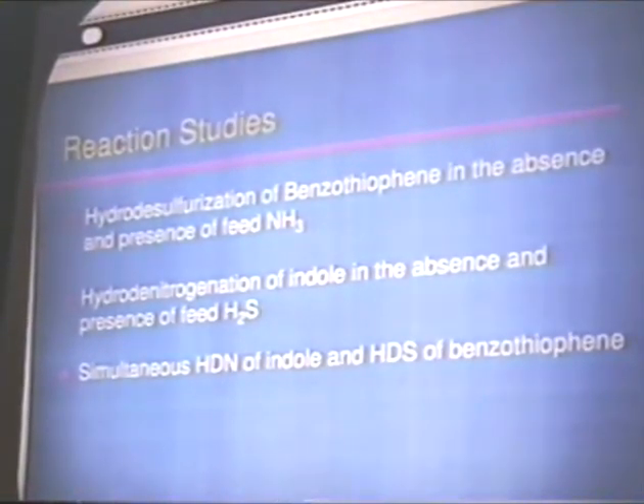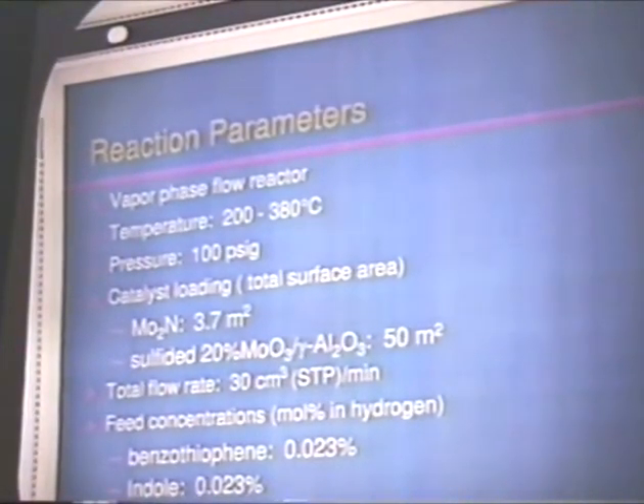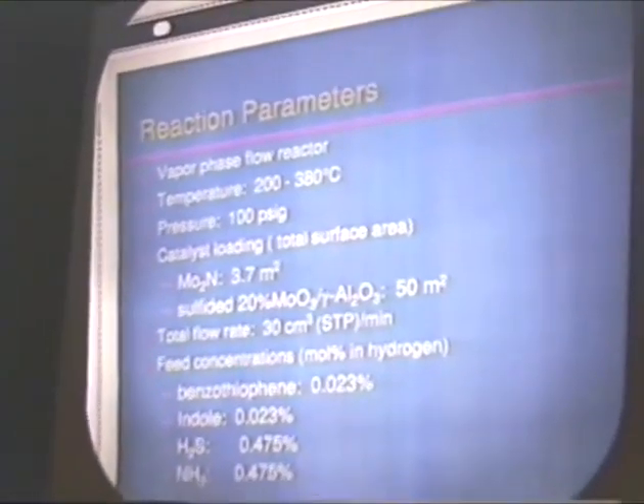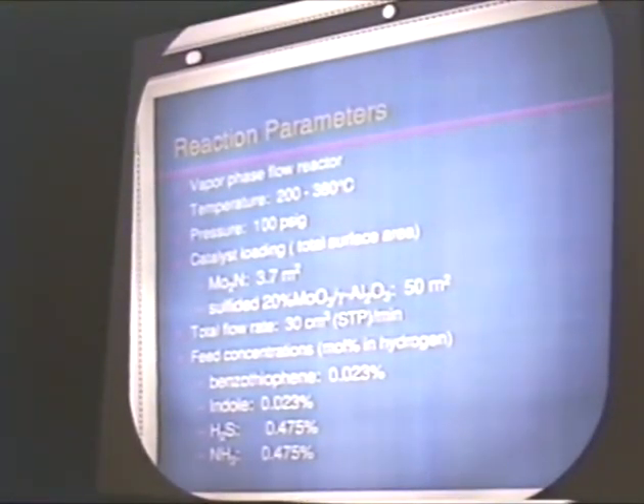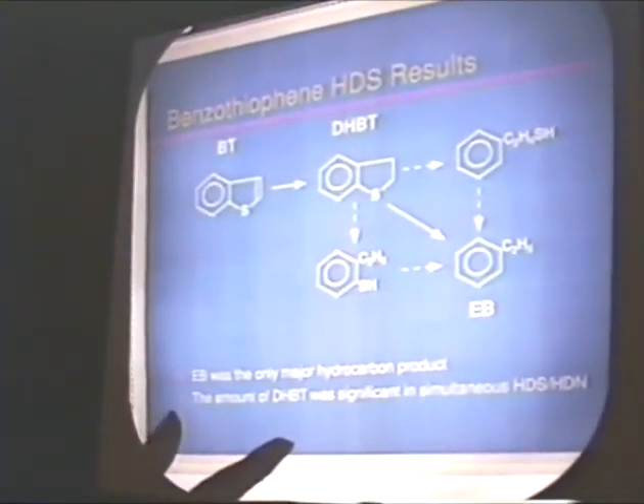Now, let me move on to reaction experiments. There are basically three groups of experiments that I will talk about: hydrodesulfurization of benzothiophene in the absence and in the presence of feed ammonia, hydrodenitrogenation of indole in the absence and presence of feed H2S, and then a third group of experiments where we have looked at simultaneous HDN of indole and HDS of benzothiophene. Reaction parameters quickly: vapor phase flow reactors, temperature range 200 to 380 degrees centigrade, pressure 100 psi. Again, catalyst loading is different for the nitride and the sulfide catalyst, but we were trying to achieve equal conversion levels. Now, let me start out by talking about the benzothiophene HDS results.